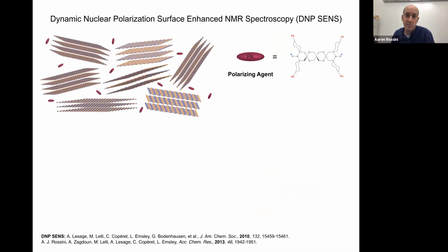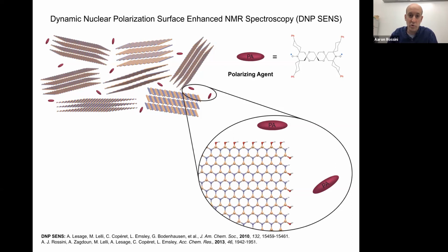And we can address both of these problems using the dynamic nuclear polarization surface enhanced NMR spectroscopy approach, or the DNP SENS approach. This was the approach developed and demonstrated by Lesage, Copéret, Emsley, and Bodenhausen in 2010. The way that a DNP SENS experiment works is we impregnate our exfoliated hexagonal boron nitride sheets with a biradical polarizing agent. In this case, it's going to be TEKPol dissolved in tetrachloroethane. This is going to put radicals on the surface and edges of these sheets. And so if we zoom in here on one of the edges of these sheets, we'll have the polarizing agent in close proximity to the edges.